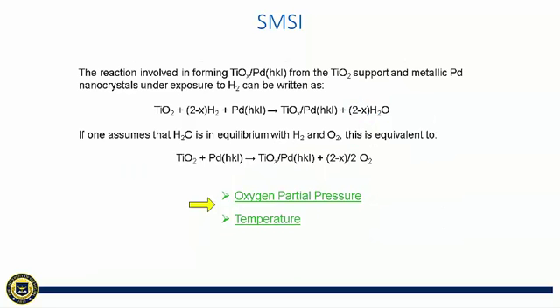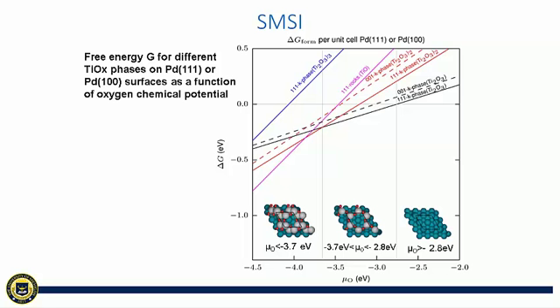And this is the reaction equation. TiO2 with hydrogen and palladium results in the formation of TiOx on top of palladium and also water vapor. If we assume that water vapor is in equilibrium with hydrogen and oxygen, then it's equivalent to the second reaction equation. Here we can see the equilibrium of this reaction only depends on the oxygen partial pressure and temperature.